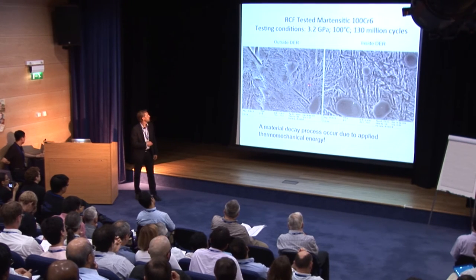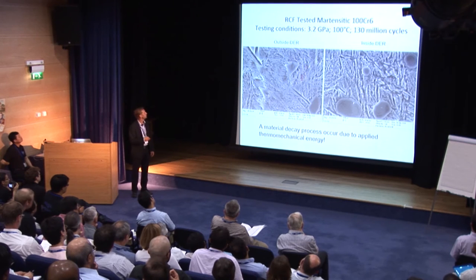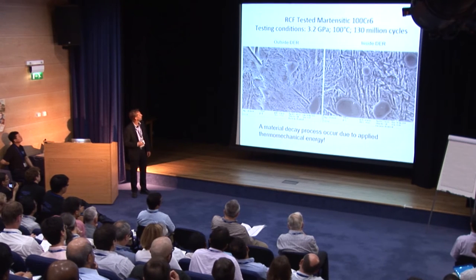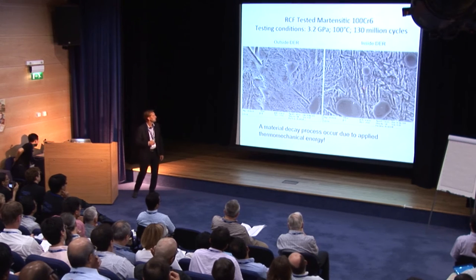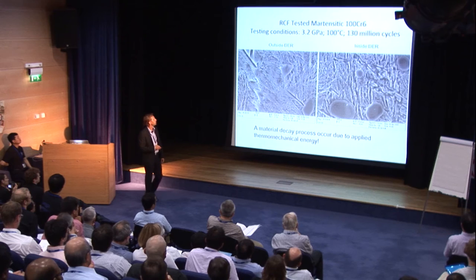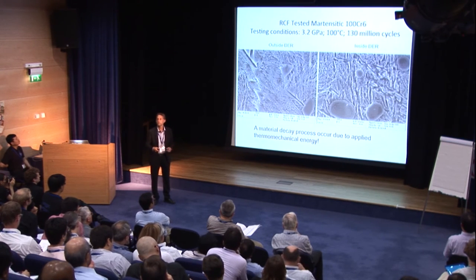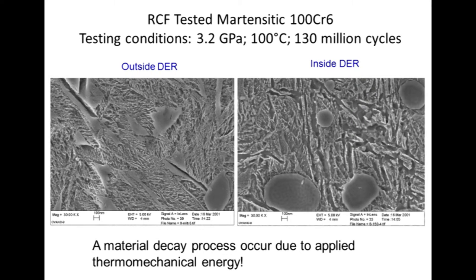Now you see the retained austenite, you see the residual carbides, and you see the martensitic structure. If you move then into the dark etching region, you have a much coarser structure. Something has happened. This is not a continuum. This is not a fracture mechanics process where a crack has formed here. You see the residual carbides, you see a much coarser microstructure, and you see the absence of the retained austenite. So the material is gradually changing.